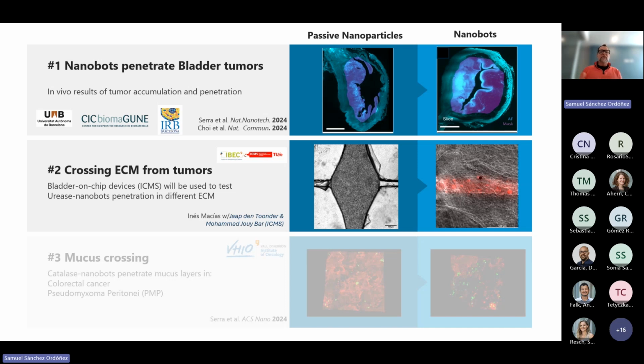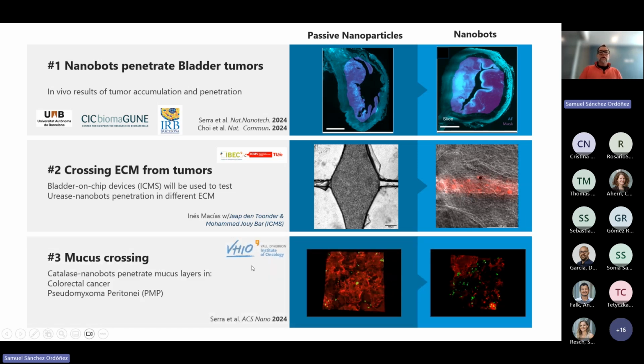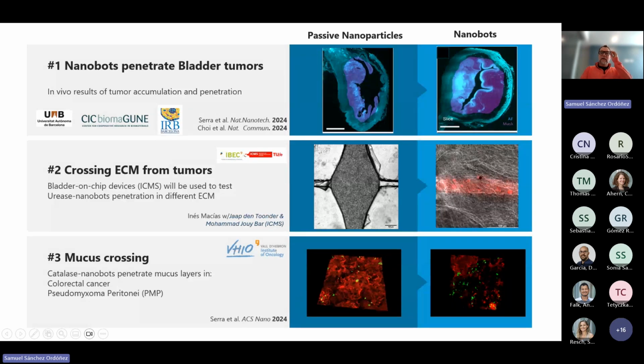We can have bladder on a chip or any type of organ on a chip, and tune the stiffness of the matrix and see the diffusion of these nanobots penetrating through this tissue in a very controlled manner. We also have, in collaboration with ICMS in Eindhoven, with Vall d'Hebron, a project, and it's an ERC proof of concept as well, where we had, instead of urease, catalase. Catalase takes the ROS or the peroxide, which is endogenously generated, or you can co-administer, and we can cross the mucus layers. Here in red, you see the mucus, and on the left column is the passive nanoparticles, on the right column are the nanobots.